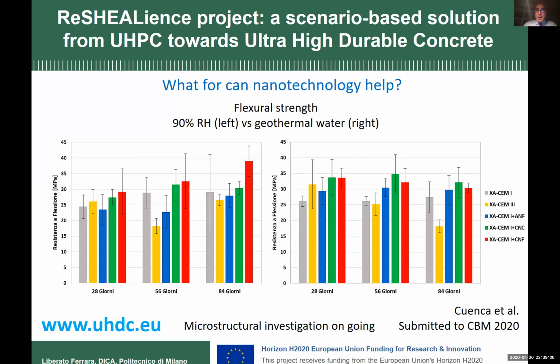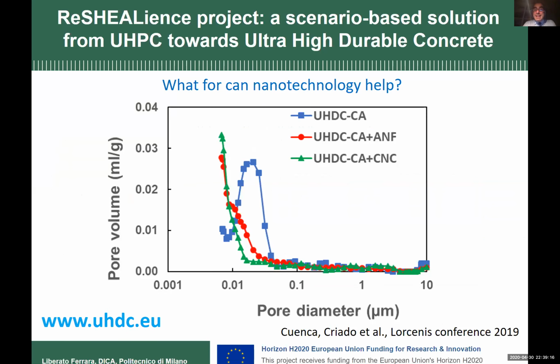This is where the nanofibers really did their job. So we have to look into the right performance to understand the effect of these materials. What is this effect due to? Well, for sure you can see there is a pore refinement, because the reference mix is the blue curve, and the mixes with alumina nanofibers or nanocellulose are the green and red curves.